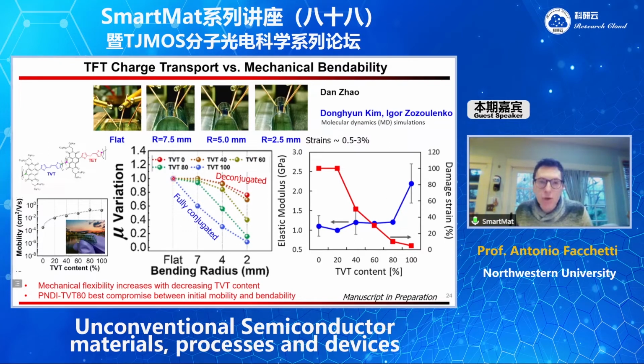And if you make the transistor with the fully conjugated component only, the mobility decreases very, very fast. And if you make the transistor with only the red component, the mobility decreases much less. And in between, you are in between in terms of performance. So basically, by deconjugating the polymer backbone, you can pick up in the elastic behavior.